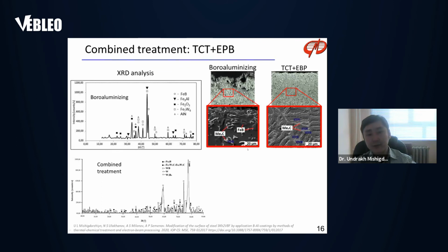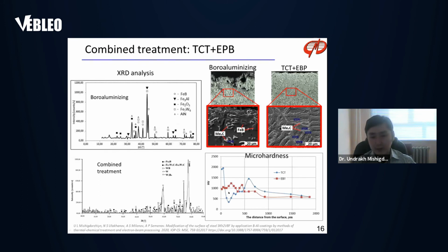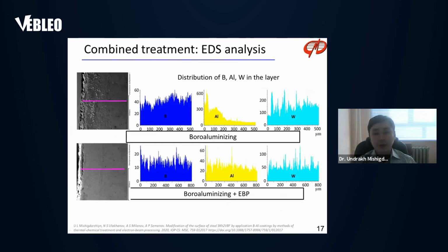The magnified SEM picture showed that solid phases such as iron borides and carbides became much smaller after electron beam processing, and this contributes to the micro-hardness distribution. As you can see, the red line shows values after combined treatment, and this pattern is much more even compared to the micro-hardness profile after first step boroaluminizing. Let me point your attention to aluminum distribution. After the first step, boroaluminizing, aluminum is mostly concentrated in the top of the layer, and after electron beam processing, aluminum concentration became more even.